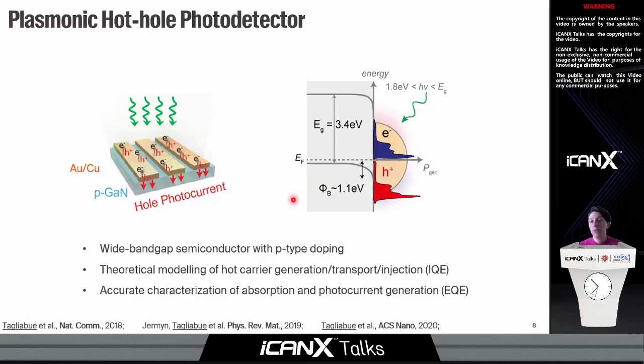So as I mentioned, if we want to understand how holes are transferred to the semiconductor, we then need a p-type semiconductor. And also what is important here is that we're interested in generating charges in the metal, so the semiconductor should not absorb any light. Therefore, we need a wide bandgap semiconductor with p-type doping, and there are very limited choices, and our choice fell on p-type gallium nitride. The second thing we wanted to do was really to combine highly accurate experiments with full theoretical modeling of both the hot carrier generation, transport, and injection at the interface in order to be able to really understand which type of carriers were being transferred.